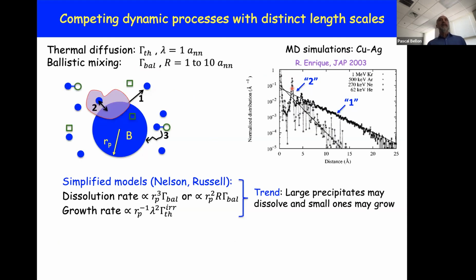I want to revisit briefly this idea of competing dynamic processes, because it's essential to the reason why these alloys self-organize. We have these processes 1 and 2, let's say, that would contribute to dissolution, and 3 to the growth of these precipitates. There are simple models that can be written down describing the expected dissolution rate and growth rate of those precipitates as a function of the jump frequencies of atoms in the matrix.